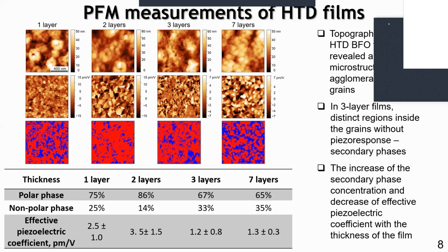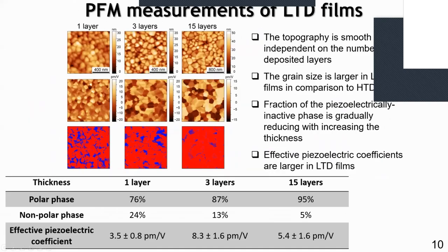50. It actually depends. But why so rough? This is a thin film, yes. So this is polycrystalline. In comparison of the two sets, the first set is more rough because of the process of fast evaporation of the liquid, which creates agglomerates of the particles. This is after heating. In the other case, the roughness is not so high, but nevertheless.